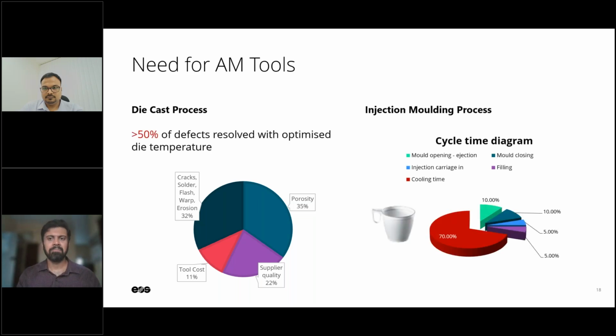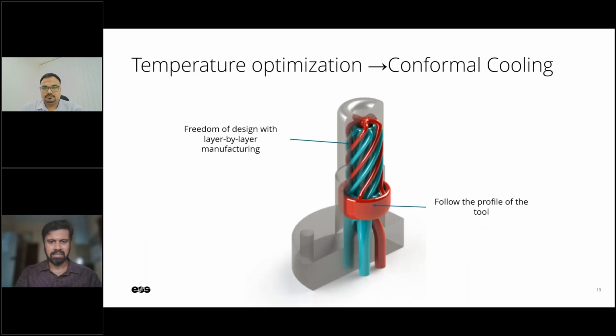In terms of injection molding, the requirement is a bit different, although we don't see a direct quality improvement being contributed by conformal cooling. Sometimes it is definitely there for a bit complex, bit large parts, thin wall geometry, and so on. But the larger contribution is by productivity, by reducing the cooling time altogether, reducing the non-value add time. So one example is this that I came across, very beautifully designed, right? How can somebody design this conformal cooling geometry? Very, very complex, right?